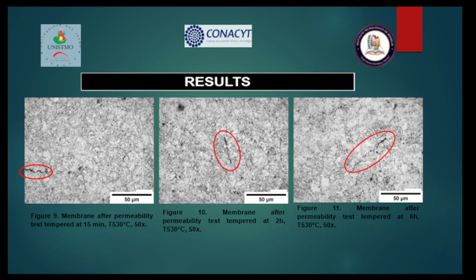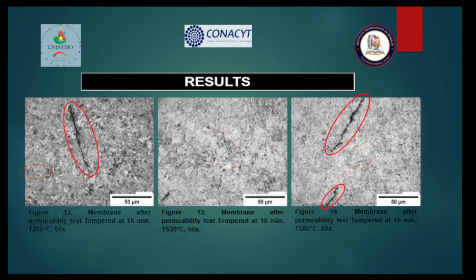Also, we have the micrographs of the membranes that were tempered at different times at a temperature of 530 Celsius. Here we can observe that cracks appeared in this microstructure, which is very curious because this effect has not been reported in tempered steels. On the membranes tempered at different temperatures with a time of 15 minutes, cracks were also observed except in one of these.